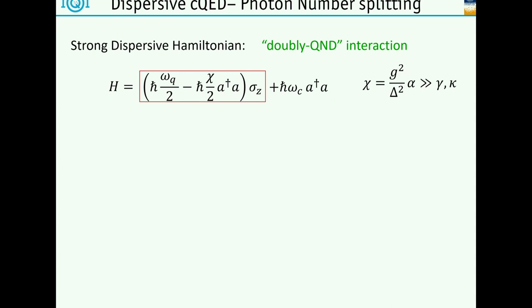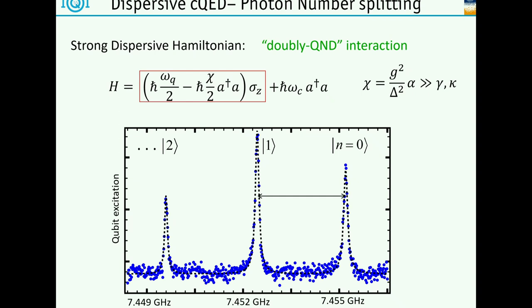So again, this chi is the dispersive shift, and we can, for example, do experiments where we put a coherent state in the cavity. In this case, it was about one photon. If we had an empty cavity, we would only see a qubit excitation peak right here. So I just excite the qubit and read it out via the cavity and see when I can excite it. I would only find a single peak if there's no photon in the cavity. But if I put photons in the cavity and they stay there while I do my spectroscopy, I can see these multiple peaks here. And the distance here is exactly this chi, as I've written it there. So this means I can use my qubit to, for example, detect the number of photons in my resonator. So I can ask the question,